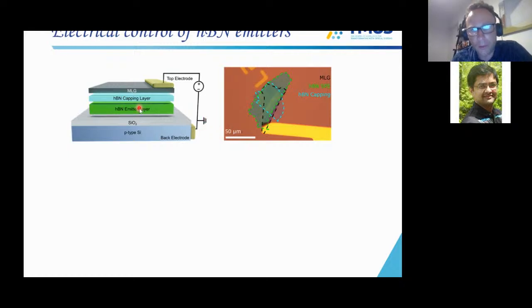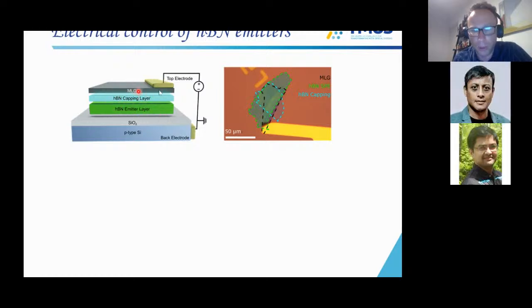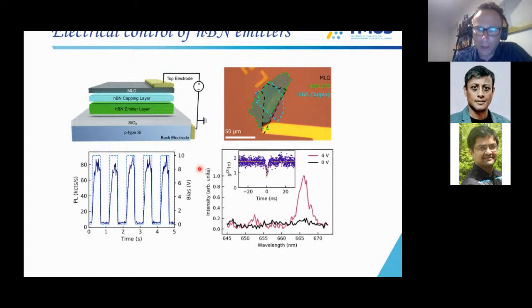So we made a very simple vertical heterostructure here with our hBN emitter layers, a capping layer, and graphene on top. So you can see it here. And what you can see is that under 0 volts, you basically see no luminescence. But as you turn the device on, at a very low bias, only 4 volts, you can modulate the emission on and off.